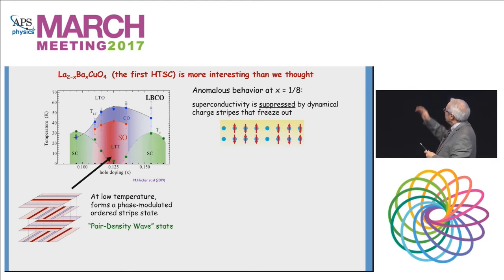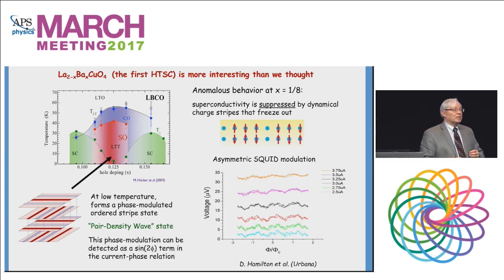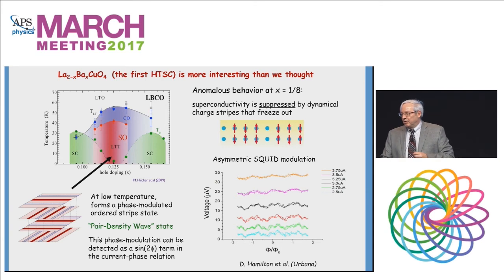And if you think about tunneling into this, you can see that along this edge, there's these stripes that have alternate phases, and so you're going to get a modulation in the sign of the order parameter. So we've been doing the asymmetric SQUID modulation experiments in our group. One of my students, David Hamilton, and we are now seeing some evidence for this as we change the temperature, and the critical current drops at higher temperatures. You can see it goes from a very clear sinusoidal current phase relation to something which has this other bump in here, and if you Fourier transform, it has a very distinct sine 2 phi term. So we think this is the first evidence for this pair density wave state.